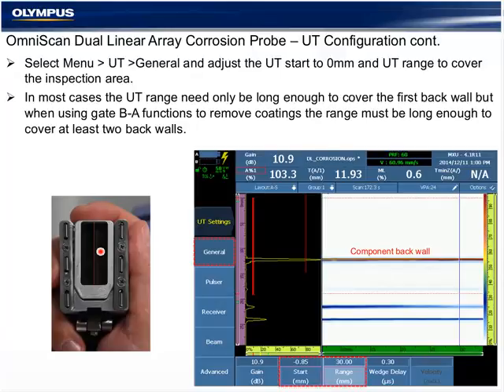And it allows a mechanical focus inside the wedge for specific thickness. In most cases, setting the UT, it need only be long enough to cover the first back wall in most cases, and it's pretty common to increase the range for the second back wall, especially if a coating or paint thickness is needed to remove the reading, the coating from the reading.